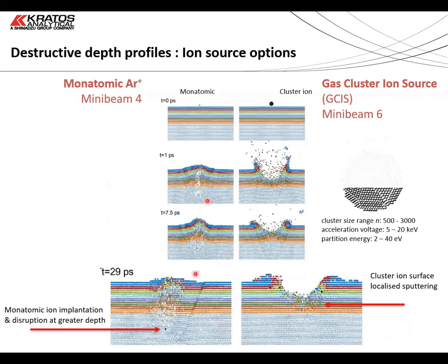Monatomic ions, the more common projectile for depth profiling, tend to create a collision cascade with the momentum focused towards the bulk of the material. In delicate polymer samples, the energy of the monatomic ion can cause significant damage to the chemical structure of the polymer and drug matrix. Using our larger cluster ions, models show that there is very little penetration into the bulk of the material, and this is a much more gentle sputtering process. The use of cluster ion sources has opened up the possibility of successfully depth profiling polymer materials.